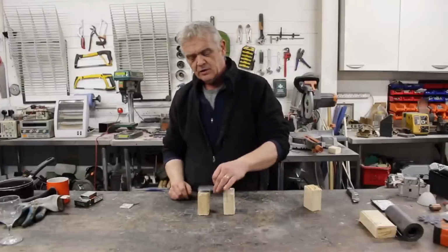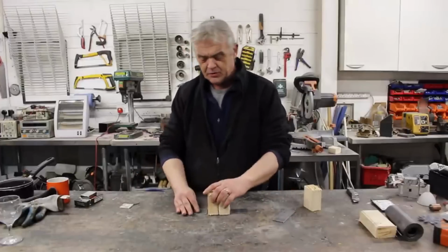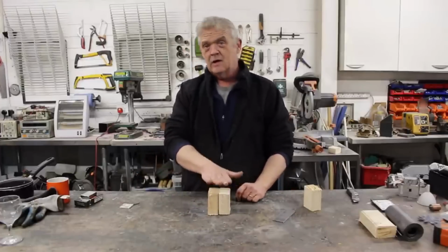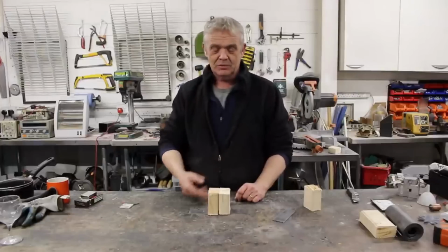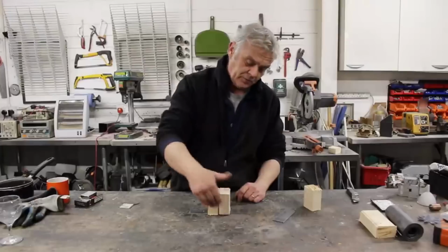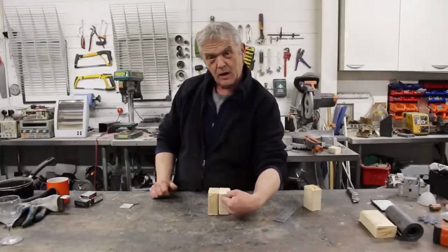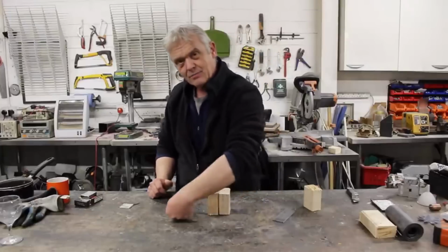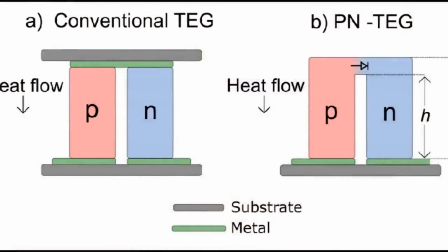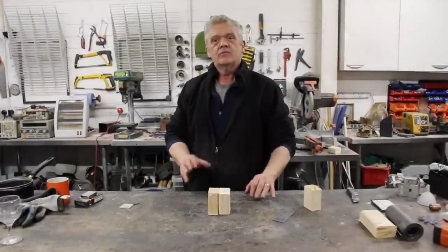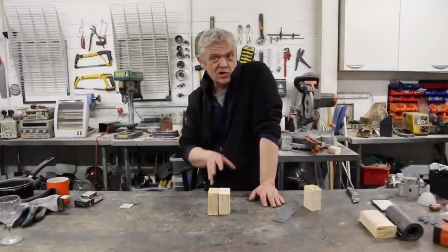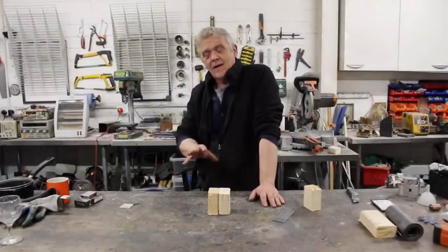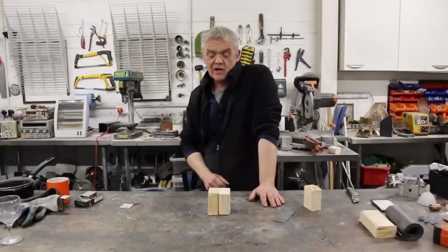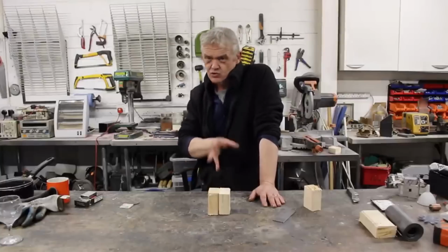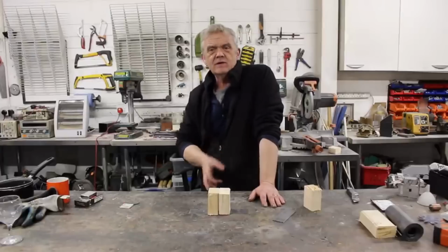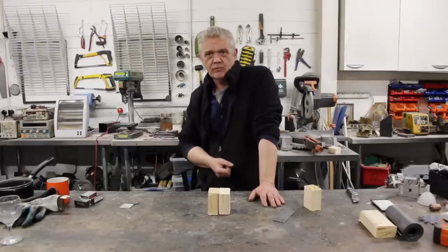There is another way. You can remove that, bang them together, put the contacts there, and heat goes there. This is cheaper and simpler because of course there's no top plate. Same thing, heat flow from the top to the bottom drives a current from here, but now it drives it across the PN junction and then back out again. And these are obviously called PN TEG architecture. But they remain semiconductors, and because they're semiconductors, they have that temperature limit on them. Now they do generate an awful lot of amps, well, microamps, but they do generate a lot for what they are, but they have a severe limitation for the application that we want to use them for.